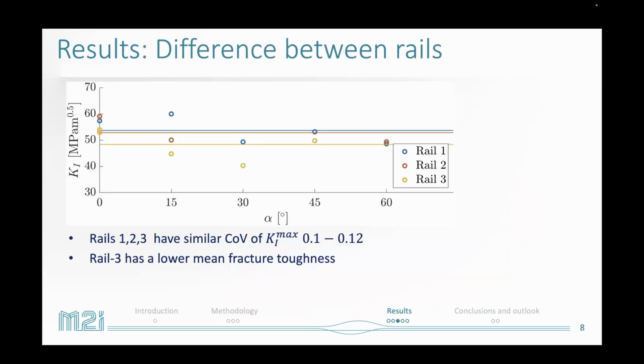Then, as I introduced in the beginning, we used used rail, and I had 13 specimens in total, coming from 3 rails from practice, fabricated between 1990 and 2010. And with these lines, you see the mean average K1 max for the 3 different rails. And you do see that one of the rails has a lower mean fracture toughness. All rails have approximately the same coefficient of variation, between 0.1 and 0.12.